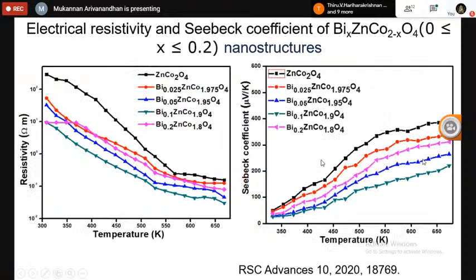Okay, and the electrical resistivity and Seebeck coefficient of the sample have been measured. And look at the electrical resistivity. The electrical resistivity of all samples has decreased, which shows the semiconductor behavior of the sample. And with respect to the bismuth content, the electrical resistivity has decreased up to 10% and slightly increased due to the secondary phase formation.